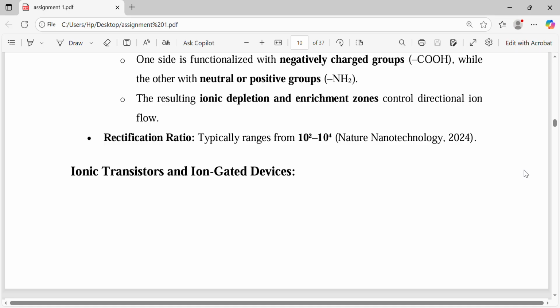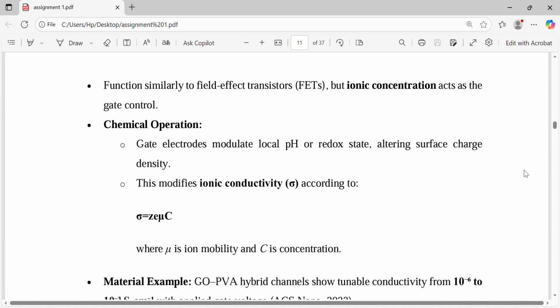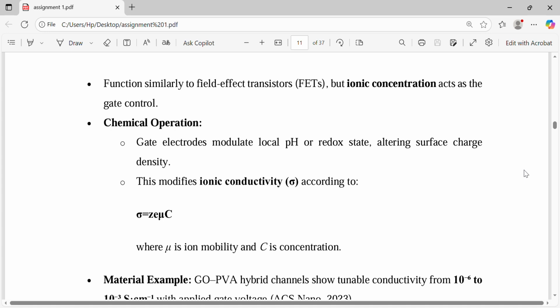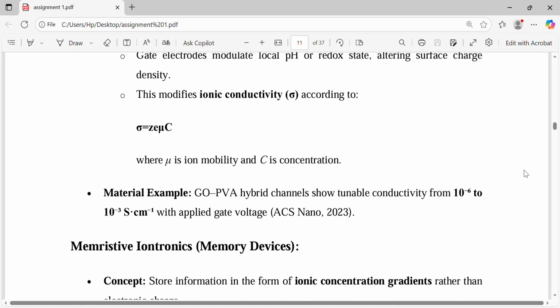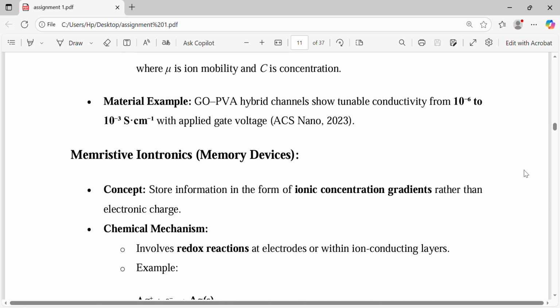Ionic transistors and ion-gated devices function similarly to field effect transistors, but ionic concentration acts as the gate control. Chemical operation: gate electrodes modulate local pH or redox state, altering surface charge density. This modifies ionic conductivity according to σ = μC, where μ is ionic mobility and C is concentration. Material example: for example, GO-PVA hybrid channels show conductivity from 10^-6 to 10^-3 S per centimeter with applied gate voltage.